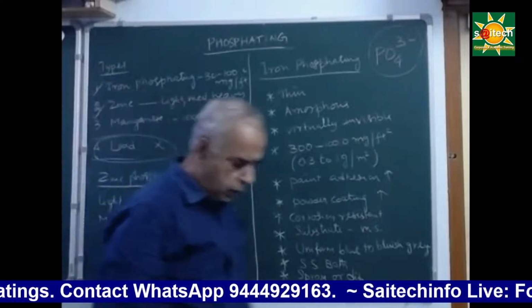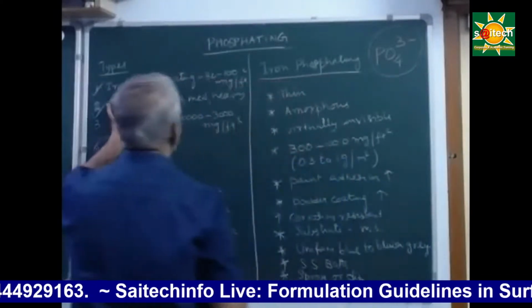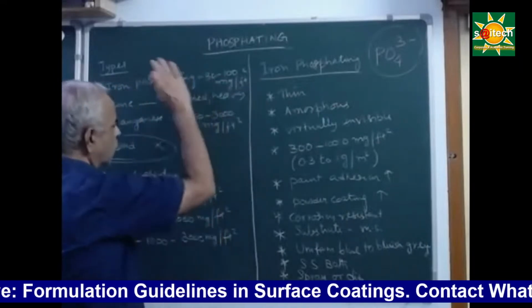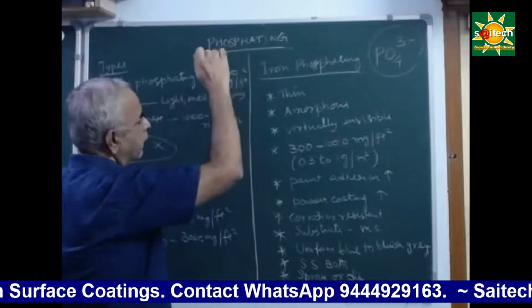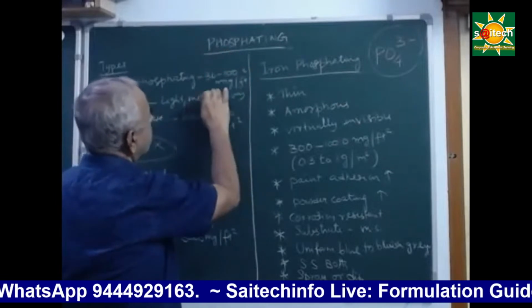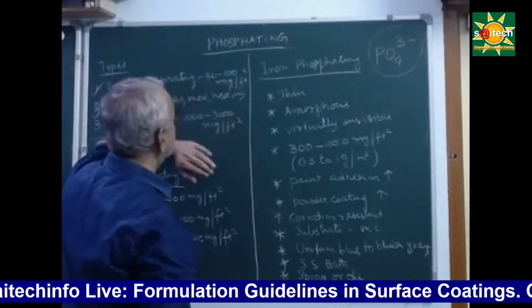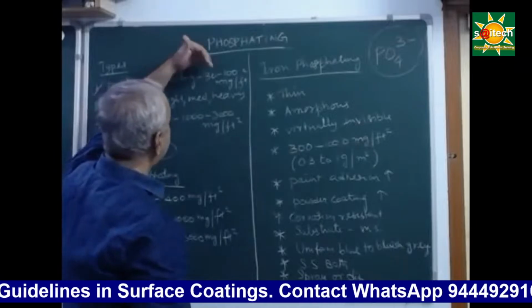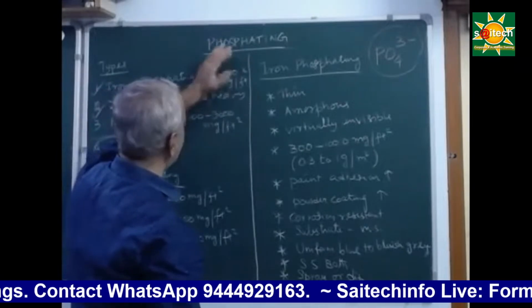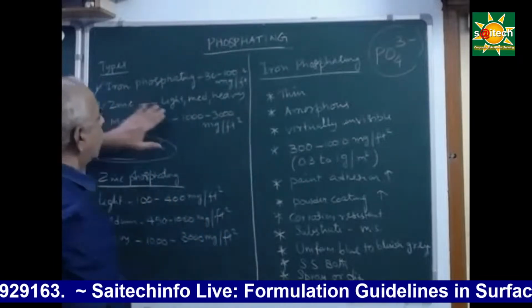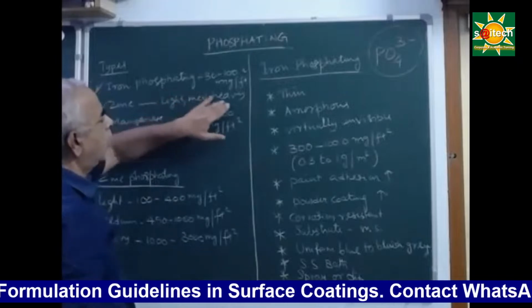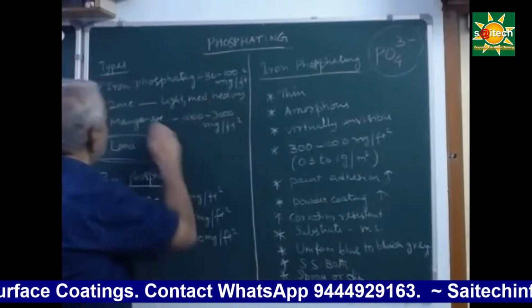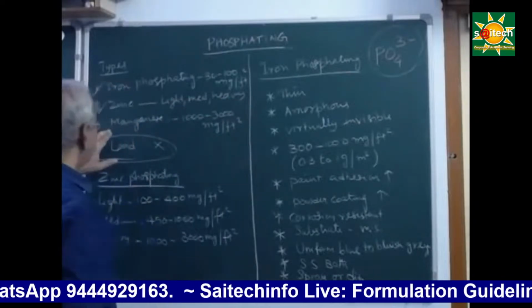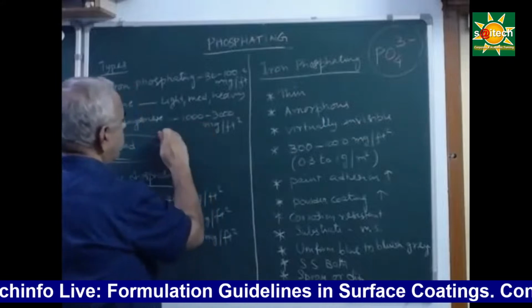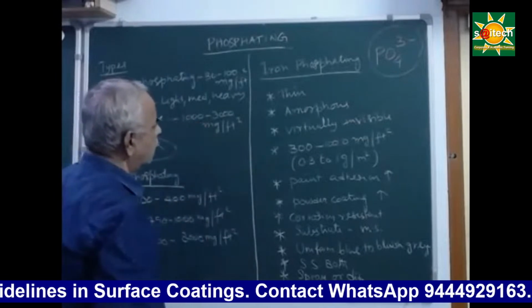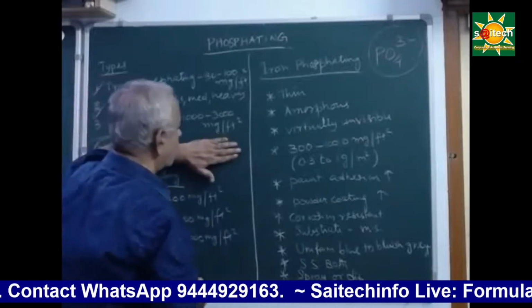In iron phosphating, for instance, the tentative coating weight will be almost 30 to 100 milligram per square feet. Even it may vary, up to 300 to 1000 also. It depends on the type of coating. Then zinc has light weight, medium weight, and heavy coating weight formulations. So there are three types of zinc phosphate coating. And manganese phosphate coating is a heavy coating. It is exclusively meant for oiling and greasing, so it is not meant for any painting.